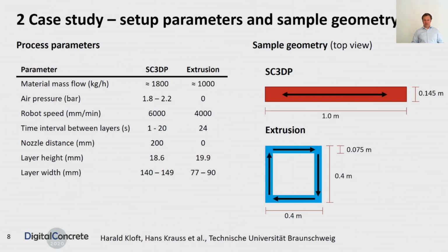As a consequence, we produce different sample geometries, because in the case of shotcrete 3D printing, the strand was broad enough to produce linear strands of 1 meter length by moving the nozzle back and forth. In the case of extrusion, we had to produce rectangular specimens by moving the extruder head only in one direction, and the edge length you can see here.